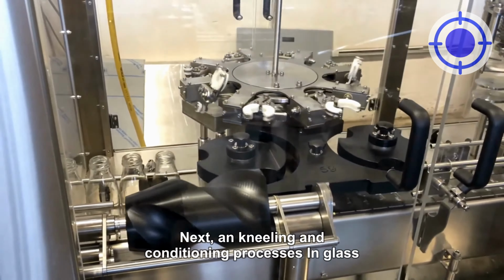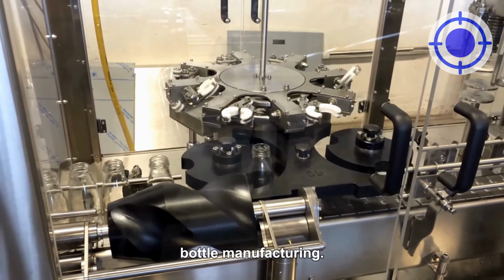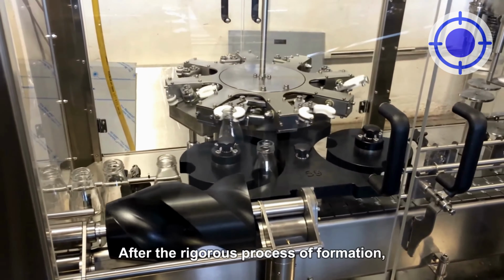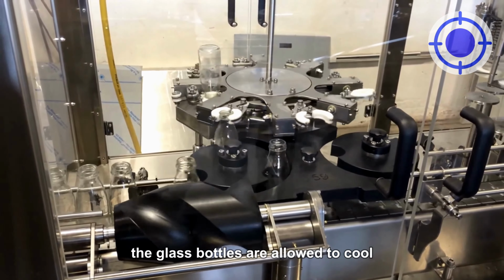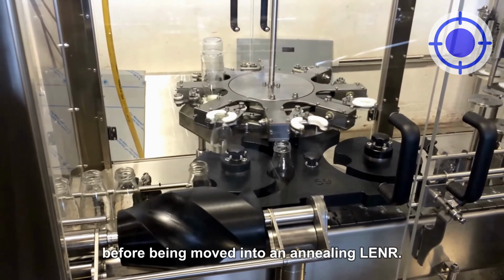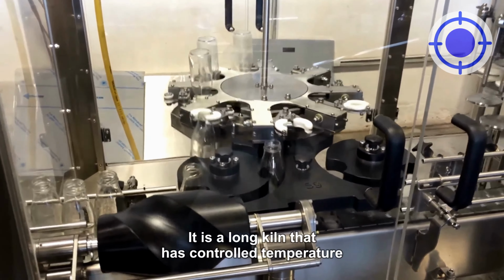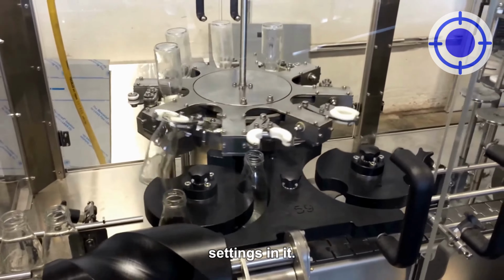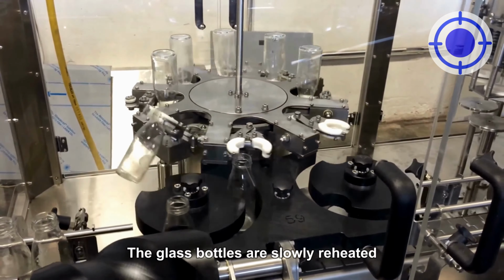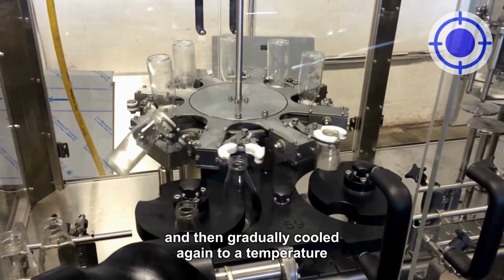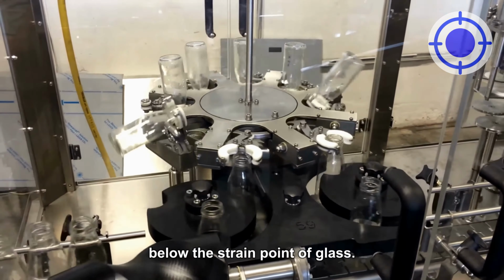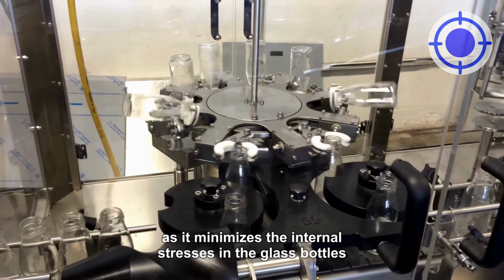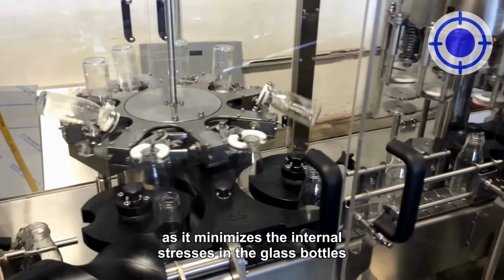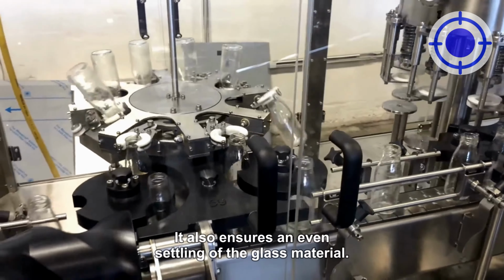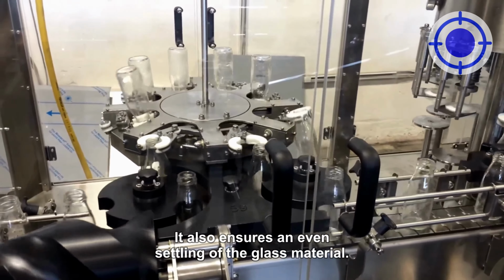Next, annealing and conditioning processes in glass bottle manufacturing. After the rigorous process of formation, the glass bottles are allowed to cool before being moved into an annealing lehr. It is a long kiln that has controlled temperature settings. In it, the glass bottles are slowly reheated and then gradually cooled again to a temperature below the strain point of glass. Annealing is important as it minimizes the internal stresses in the glass bottles that can lead to shattering. It also ensures an even settling of the glass material.